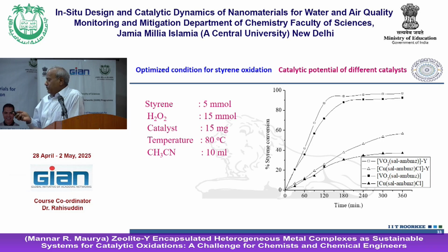In that case, you will find that styrene to H2O2 we are using is 1 to 3. The conversion is very good, almost 93, 94%. But since we have 3 times hydrogen peroxide, this is further oxidizing styrene to other products. But conversion is very good. When you compare, you will see that the zeolite one is working really well, and within copper and vanadium, vanadium is giving good results. So vanadium is acting as a better catalyst.